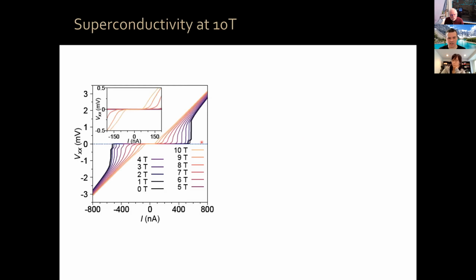Now, we can first check that indeed this is superconductivity. If you measure the critical current as a function of magnetic field, you can see that it continuously decreases, but, I'm zooming in here for 8, 9, 10 Tesla. It's very much still finite, your critical current at 10 Tesla in plane, okay?